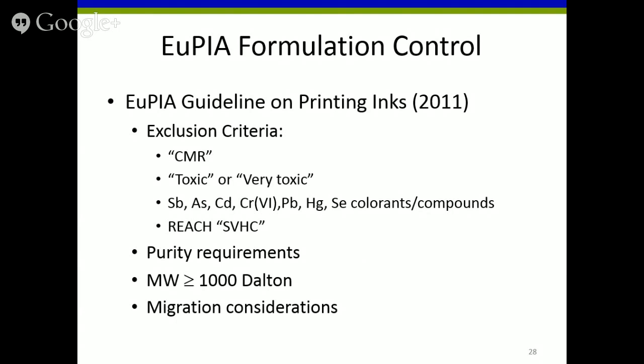Yeah. So it's about having good GMP control on the press, but also somebody's asked, are there limits for retained solvents? Are there specific limits or not? There are customer-specific limits, but to my knowledge, there are no generally accepted industry standards for retained solvents. And again, the quantified amount of solvents is a repeatable testing protocol, but that quantity is dependent upon the conditioning temperature and duration, and maybe even a temperature change with the preconditioning of the sample before the GC headspace is sampled. So there's a lot of test method art associated with retained solvent metrology that needs to be understood by the practitioners and customized for your own printing operation.